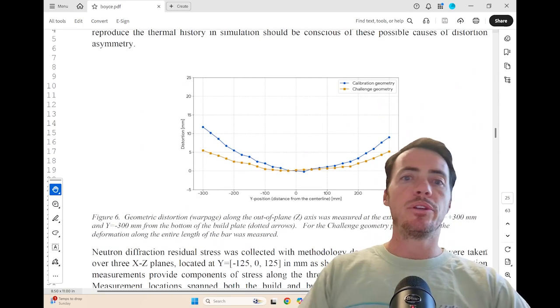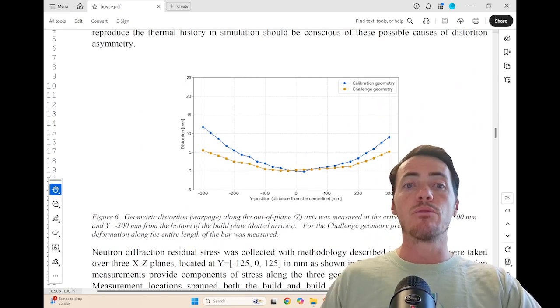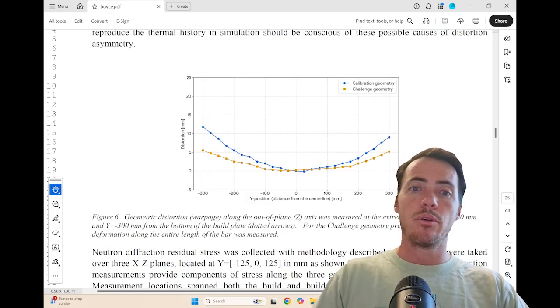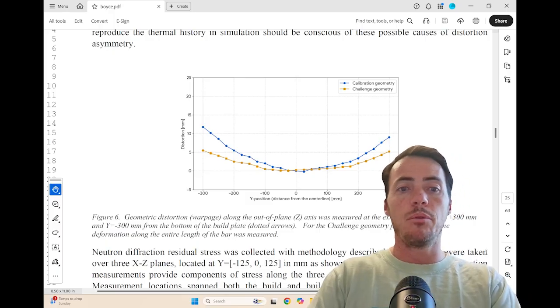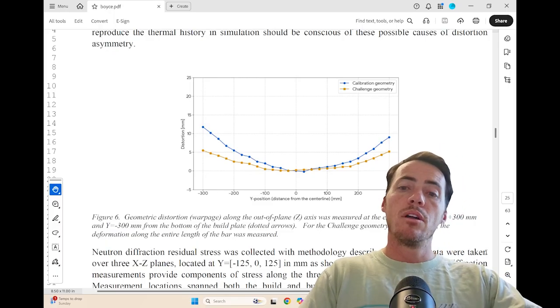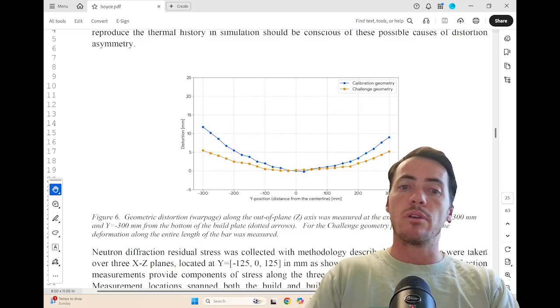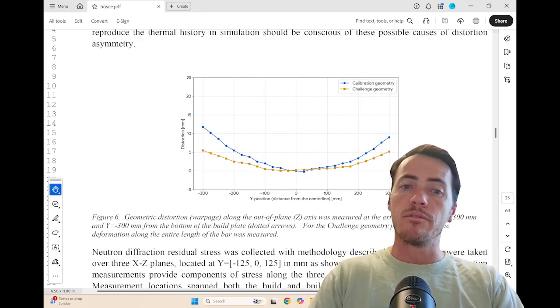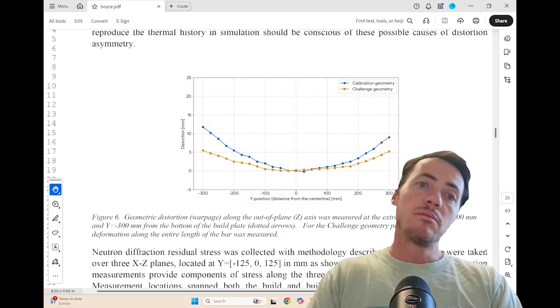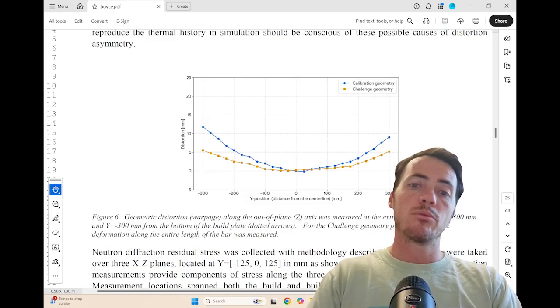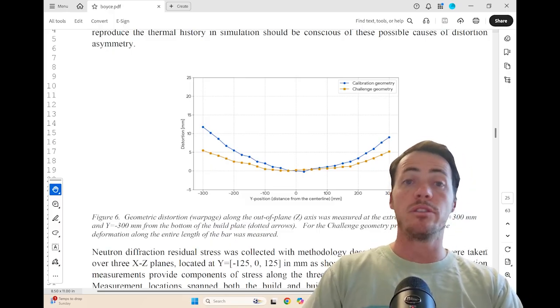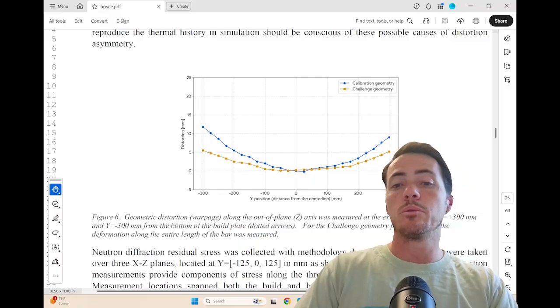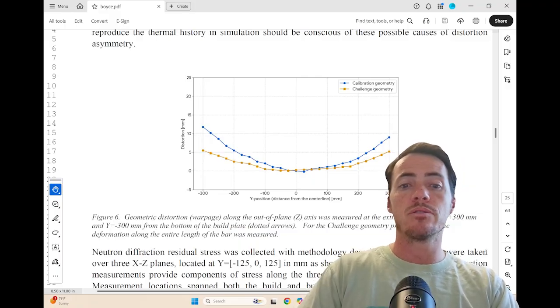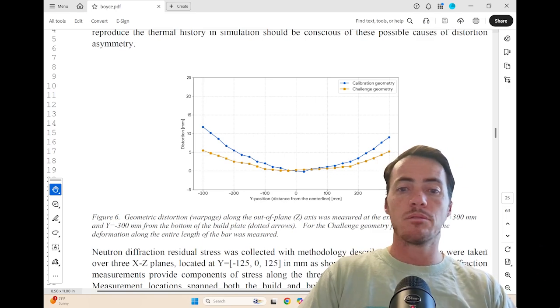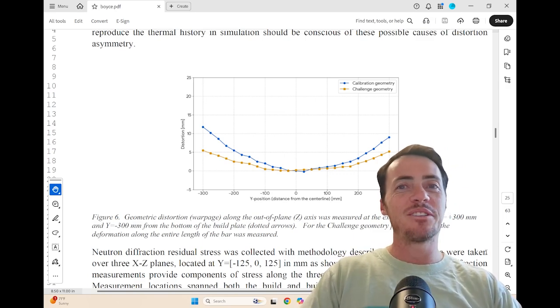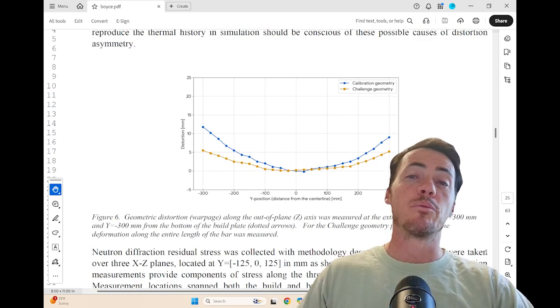So let's jump down and see how we do. They are not the same, right? You see greater distortion in the calibration sample as opposed to the challenge sample. The reason for that, again, is because you have these larger distortions because there's stress accumulation along this long axis of the part. What I think is generally impressive here is that the predictive models were able to predict warpage distortion pretty reasonably. One model was within about 7% of the measured distortion, which at first glance seems like great, a real success story. But then we get to the real challenge if we scroll down to the residual stress plots.